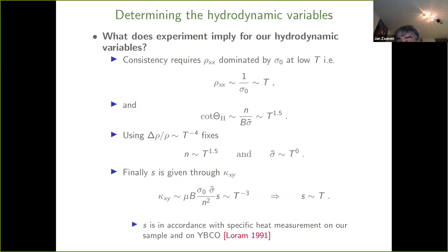I can show you pictures where you really zoom in on the low frequency regime, where you perfectly see that the initial drop off as a function of frequency really goes like an omega squared. You cannot distinguish it from a pure Drude until you are at something like 50 meV. Then this other piece is kicking in visibly. The whole optical world will agree with these things. Also when you do theory spectroscopy, all these people are saying it looks like a perfect Drude response. It's part of the standard interpretation. In the mainstream of high Tc stories about transport, everybody has been saying it's very Drude-like. You would love to see it be incoherent, but it's just not true. It's just a myth that is propagating in your community. I'm sorry about it, but this is the way it is.